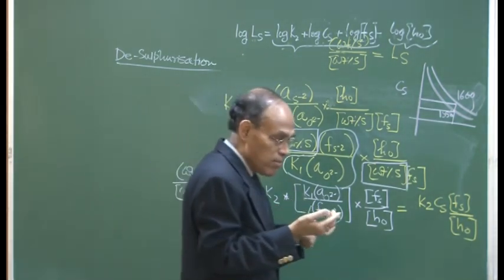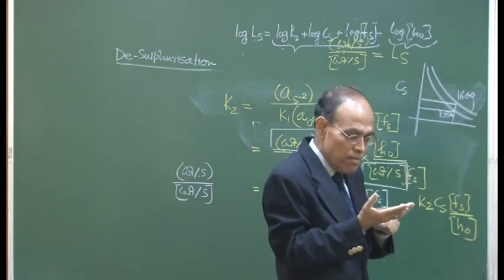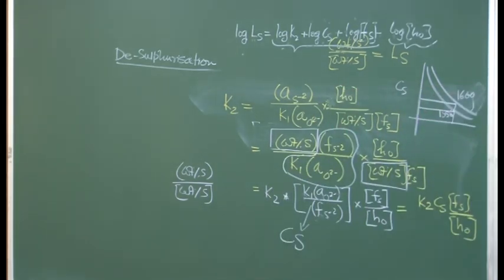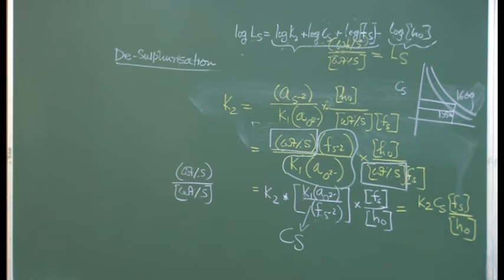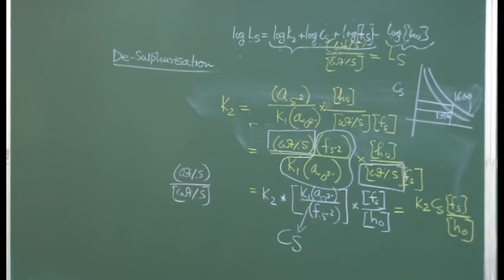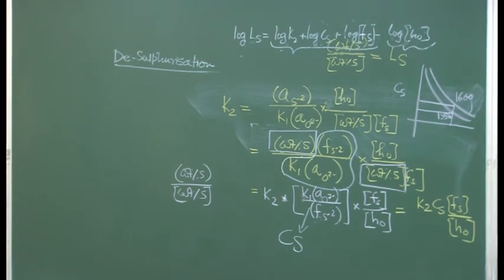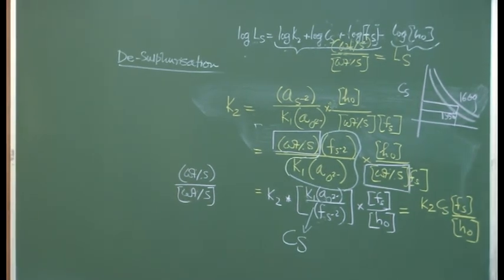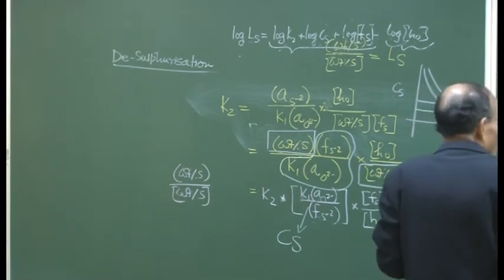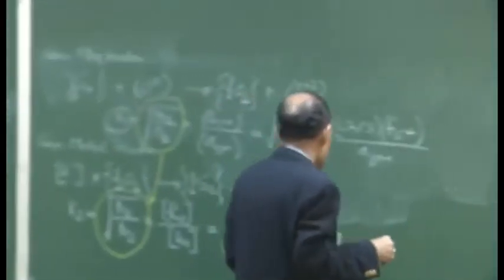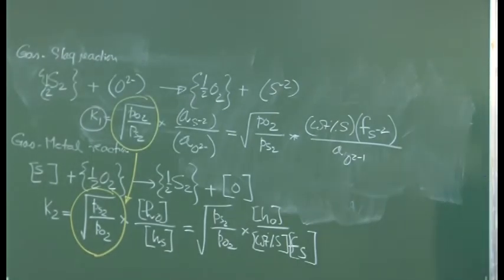So temperature, not so much though. The basicity of the slag, the oxygen potential of the metal, the activity coefficient of sulfur in the melt, and the activity coefficient of sulfide ion in the slag, these are important variables that will allow us to obtain a high amount of desulfurization in the system. So, this will tell us now what are the reagents which can be used for desulfurization.